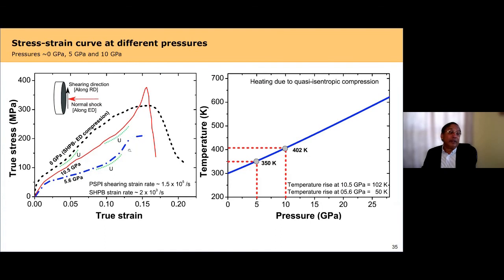Here, this is again plotting true stress as a function of true strain. This is at 5 GPa and this is at 10 GPa. We find that there are some different operating mechanisms, because there is a temperature increase which we need to account for due to the shock in the material, and also in the shock case the material is pre-compressed before the shear wave arrives.